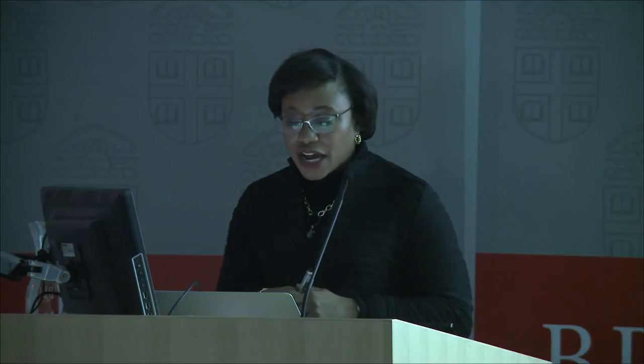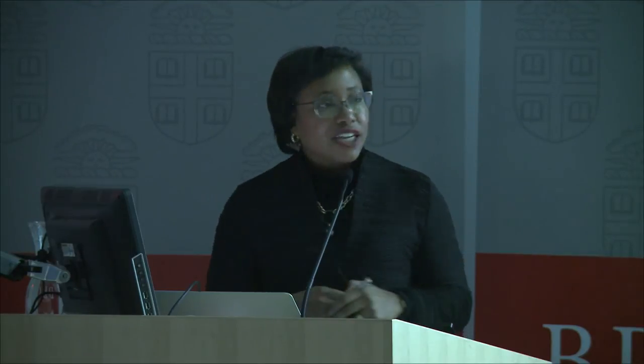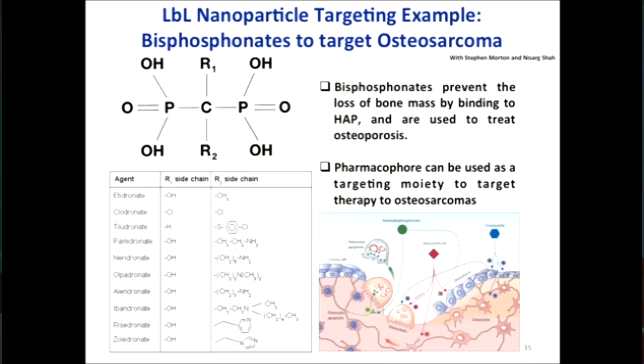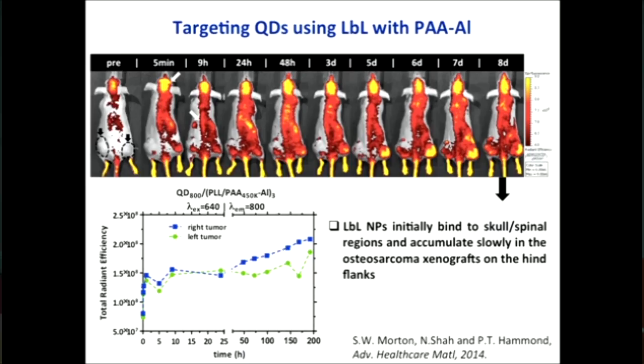So we looked at treating osteosarcoma in this fashion by using this bisphosphonate molecule that essentially binds to the hydroxyapatite deposits that are produced by osteosarcomas. So I'll make the story short. We can tail vein inject, and we're using osteosarcoma tumors that are, again, on the flanks of mice, and we see accumulation over a very long time period in these osteosarcomas.